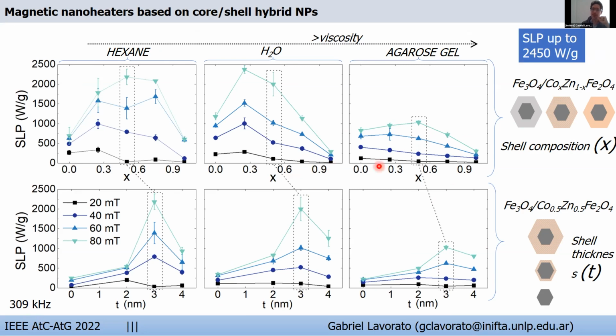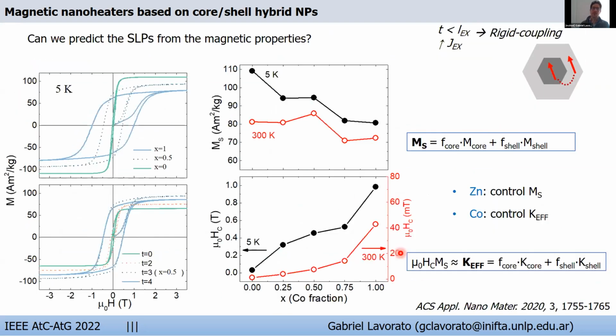So these obtained values are larger than those of single-phase nanoparticles with similar sizes, and heating powers in hexane and in water are considerably larger than those in the high viscosity medium. And for large viscosities, the low field amplitudes, we would prefer also lower cobalt contents and thinner shells. So to understand these results, we analyze the DC magnetic properties. If we have thin shells and a strong coupling, as it is our case, we can assume a rigid coupling condition, and we can estimate the effective anisotropy of the system from the measured coercivity of the whole nanoparticles.